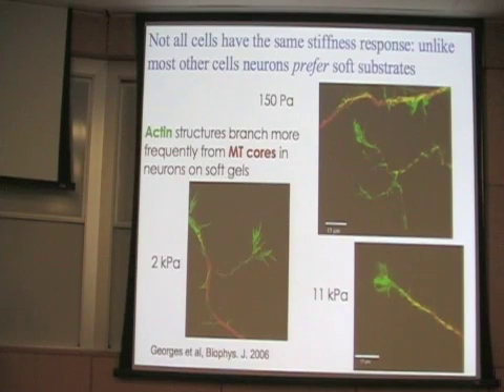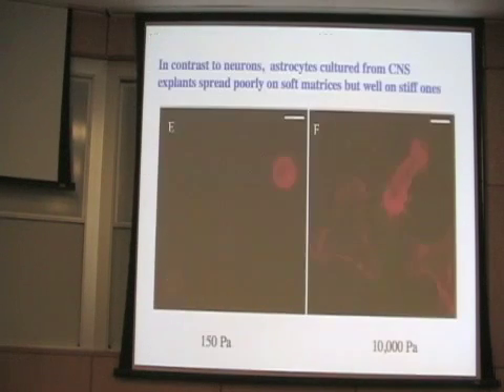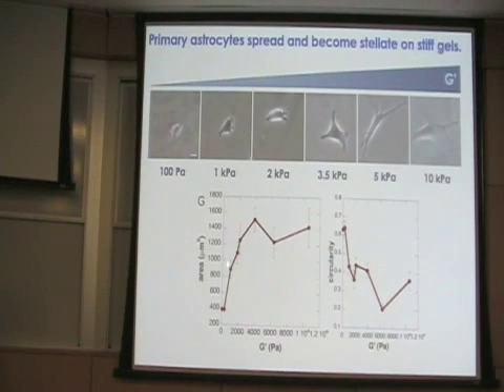As far as I know, this is the only cell type that grows out faster on soft materials than hard materials. Its neighbors in the central nervous system, astrocytes, act just like fibroblasts. They're round and unstructured, but metabolically perfectly happy. So this is a surprising thing. These cell types, which ordinarily have beautiful stress fibers and very well assembled intermediate filament systems, when you put them on something soft, they have zero stress fibers that we can see, and they depolymerize their intermediate filaments, but they're metabolically still happy.